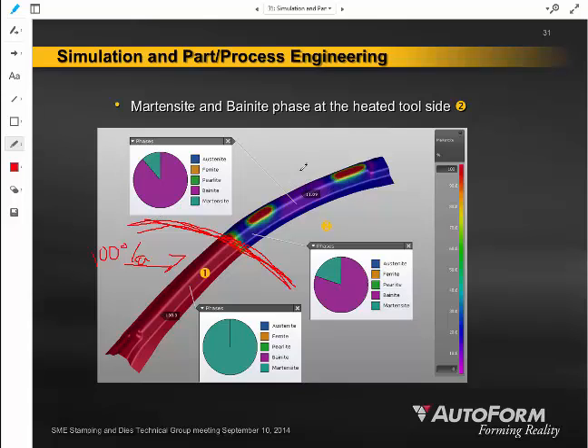But you can also notice that there are lower percentages of martensite. In this purple area, we're seeing martensite levels as low as 10%. So that material is going to be more like the original strength of the steel directly from the stamping mill, the coil mill. It's not going to have that value-added quenching characteristic of being increased in strength.